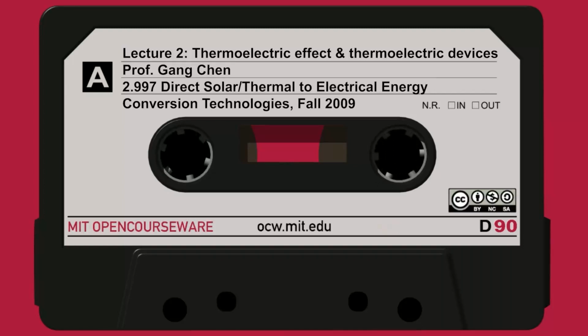So this is when material scientists just say, I discovered a material with high Z. That's S squared sigma over K. Okay, you want a material with a high electric conductivity. That's you want to minimize Joule heat. You want a material with a high Seebeck coefficient. Seebeck coefficient fundamentally is the heat carried per charge. Okay, we'll talk more on that later. So on average, per charge, how much heat it carries. And then you want a thermal insulator, a low thermal conductivity, because you don't want the heat to reverse back.